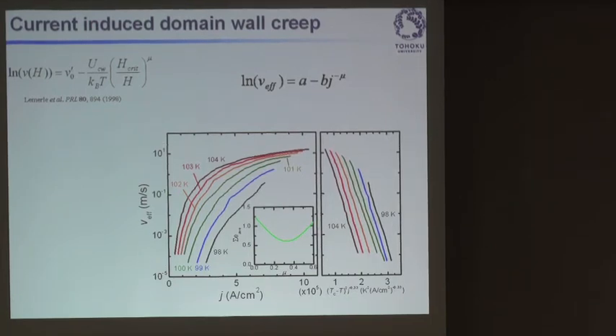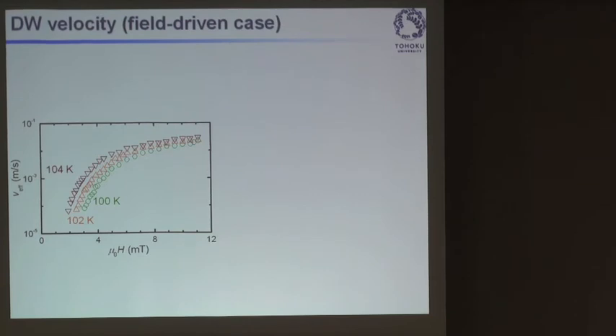And we have found that this critical exponent is 0.33. As you can see, we can collapse all the seemingly different curves into a set of curves that have the same sort of slope. So clearly, we can use this formula to scale the physics that we are seeing in our domain walls. Using the same device, we can also do a very similar experiment using magnetic field. So this is current, but we can also apply magnetic field and induce creep motion. And this is the result.